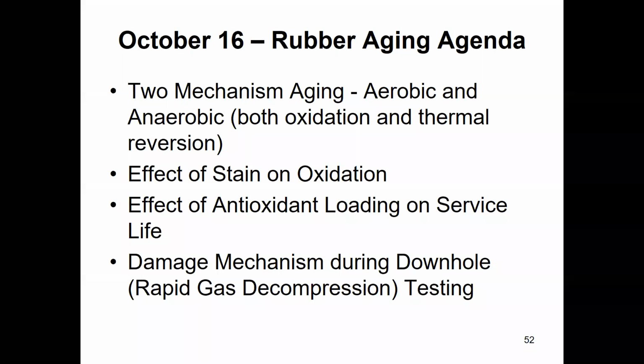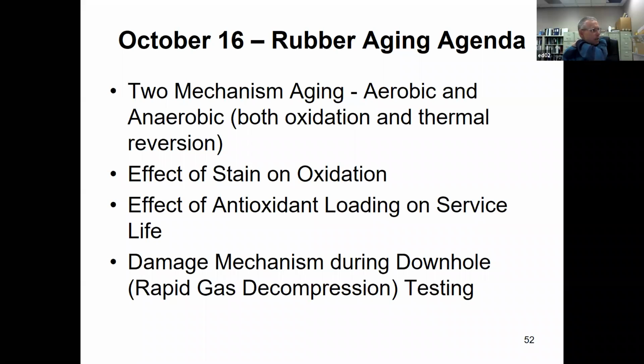The other idea that I'm hoping to try is to measure tensile properties at the same temperature, with and without UV exposure, and get a shift factor. Of course, the more temperatures you do that, the better your confidence in your shift factor.